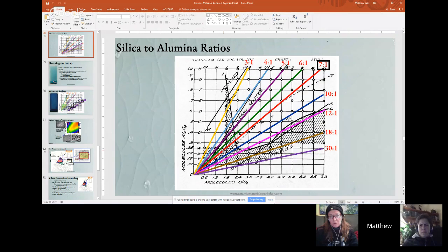Now, of course, one of the harder things about that is we're now down in this lower corner of Stull, and we can talk about trying to get glazes that are down there. The good news is that we can make glazes that are down there. We're going to have to bring in something soluble like soda ash to get into those lower corners. We can talk about the qualities of that, and as we get into the greater special effect conversations, sometimes you make chemical sacrifices for particular effects. So it really depends on what you want to do.